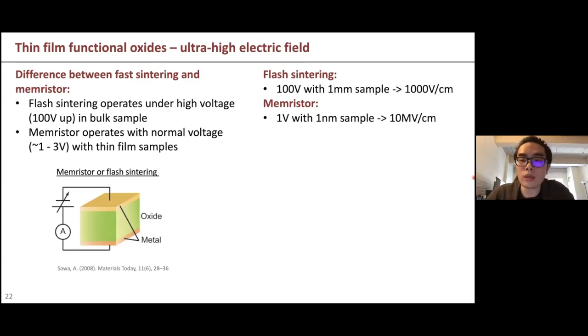So if we convert the voltage to electric field, which is basically the voltage divided by the size of your sample, for flash sintering it will be around 1 kV per centimeter. However, for a memristor, even though it is just operating under 1 volt, the sample is very, very thin. It is usually ranging from 1 nanometer to 10 nanometers. So you can see the electric field strength can range from 1 megavolt per centimeter to 10 megavolt per centimeter.